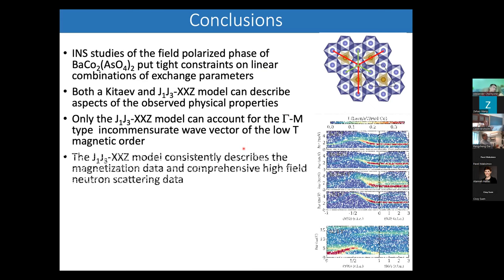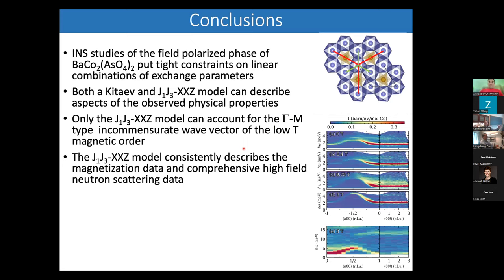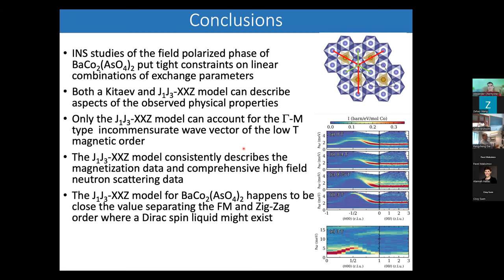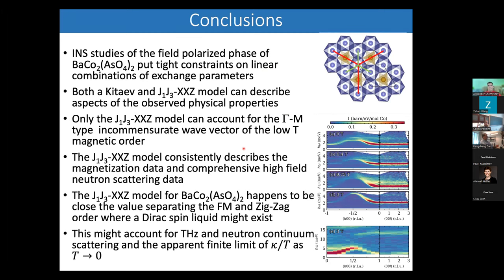And so this reveals the compound to be an easy plane ferromagnet with a significant third neighbor antiferromagnetic interaction that drives it very close to a critical point, or transition if you will, between ferromagnetic and modulated phase, where there may in fact be some kind of spin liquid physics present. So there may still be life in this compound, but we think not as a Kitaev compound, but rather as a material with competing in-plane interactions.